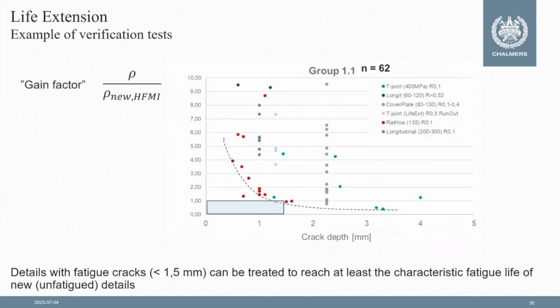Another way of showing the data is to plot the gain factor from HFMI treatment as a function of crack depth at the time of HFMI treatment. This curve shows that if we have cracks less than 1.5 millimeters, we would be able to get a gain factor of 1, which corresponds, again, to a new HFMI treated detail fatigue life.